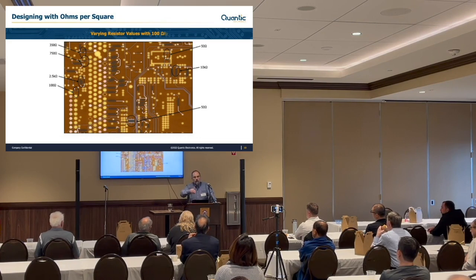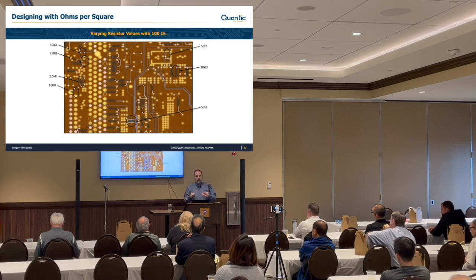So that's a process control we do every so often. We do it at the beginning of the run and then every so often. But what happens is we know there's an offset, depending on which resin system it's going to go to. For most of the standard materials, the temperature range of lamination is maybe 390F, it's not that high, but if you start going to PTFE, that gets a lot higher. So we find out on Teflon there's a bigger shift, so you can offset for that. So we know exactly, so a 25 ohm resistor might become a 28 ohm resistor material, but then you compensate for that. And we know that offset.